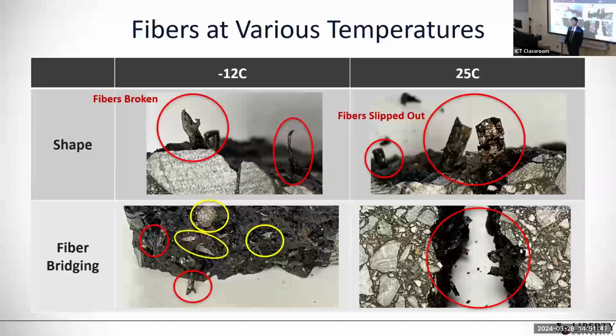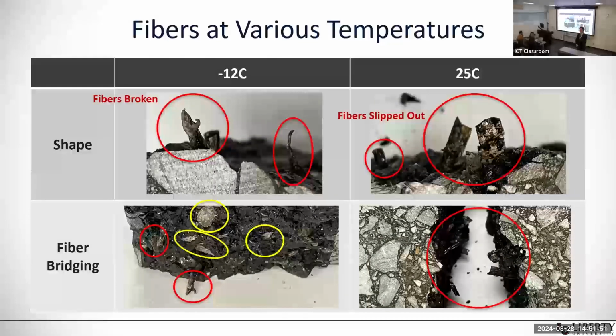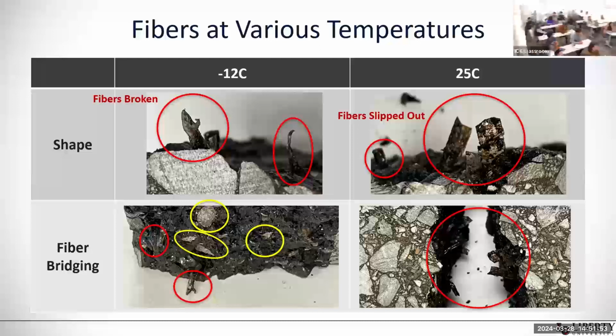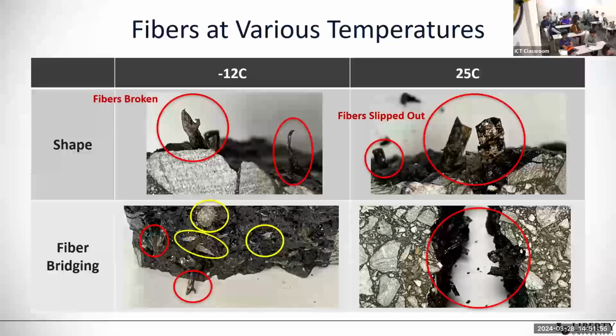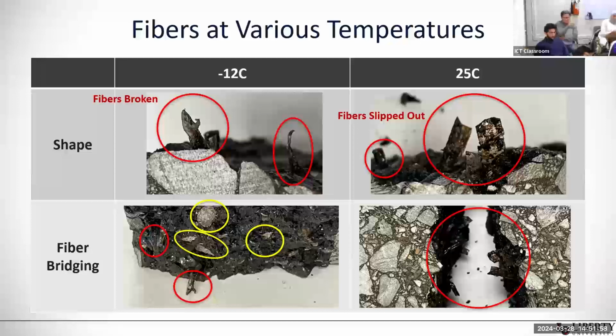Yes. If I may ask a silly question, I also had a question regarding this breakage. Did you see the binder cracks in the specimens showing significantly different modes of cracking, like more sudden or more gradual? Would that have an impact on the loading into the fiber? I assume, again, as a non-expert, that if you crack gradually, there will be more opportunity to pull the fiber out, rather than a sudden cracking under low temperature, which might put a huge load onto the fiber.